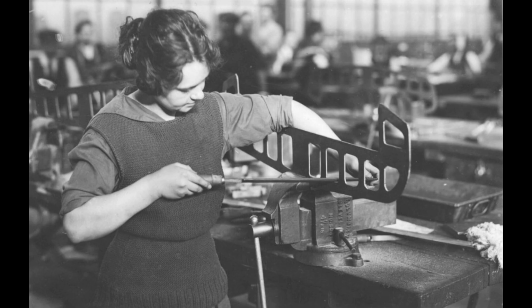The technical challenges of sustained high-volume production manifested in unexpected ways. Die wear patterns proved more complex than initial engineering calculations suggested. The center of the die cavity, where steel flow rates were highest, showed accelerated wear compared to edge areas. This differential wear gradually changed the helmet's internal contours, creating subtle variations in wall thickness. Quality control inspectors developed increasingly sophisticated measurement protocols to detect these changes before they exceeded tolerance limits.